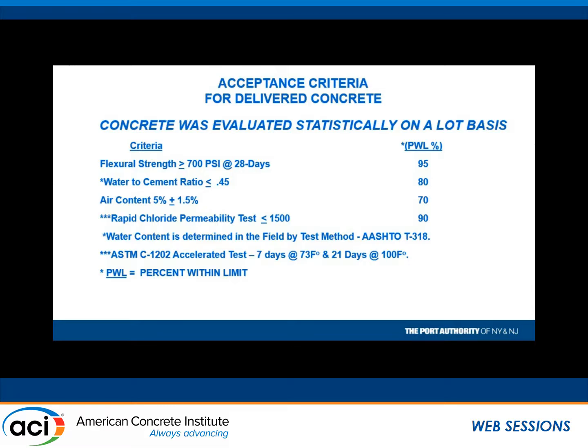So we said, look, we think that the water content must be where it was supposed to be by mix design, and that will be confirmed with the microwave test. And the air has to be where it was specified. And the other thing we added in there was the rapid chloride permeability test for one reason only, just to make sure that the pozzolan was in the mix, and that it wasn't left out by accident. So that's why we have that in.